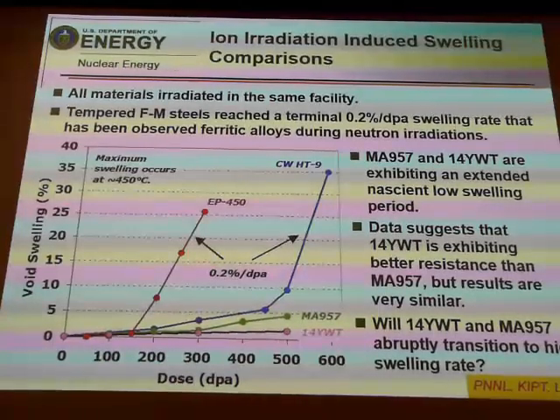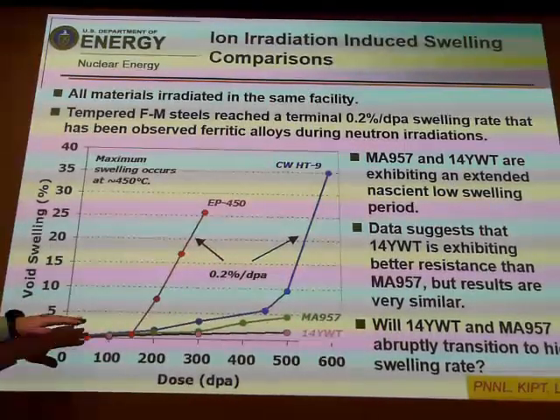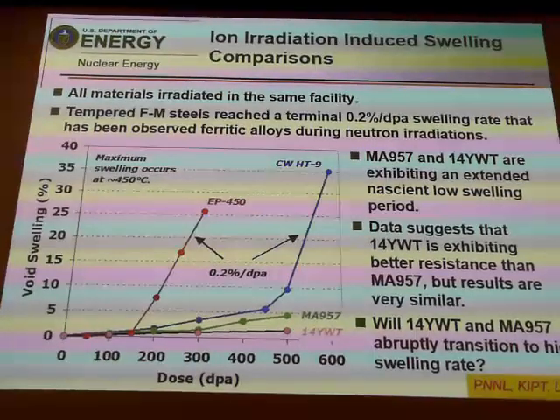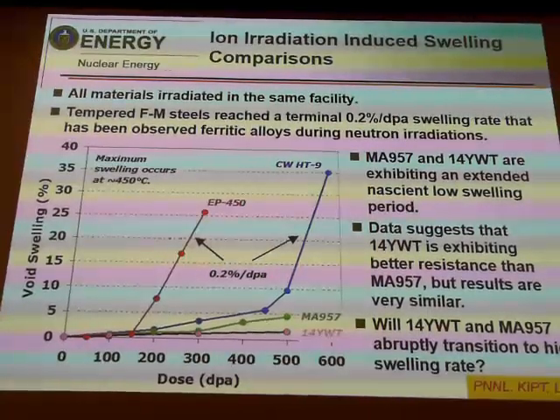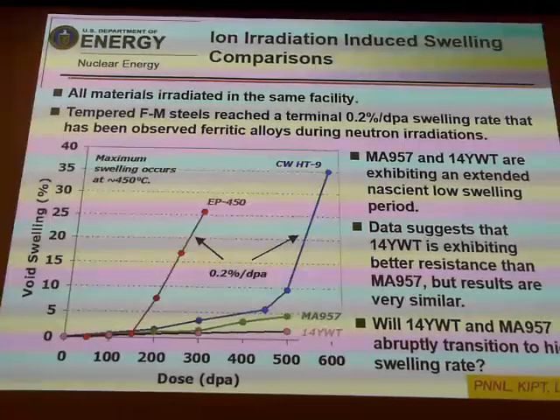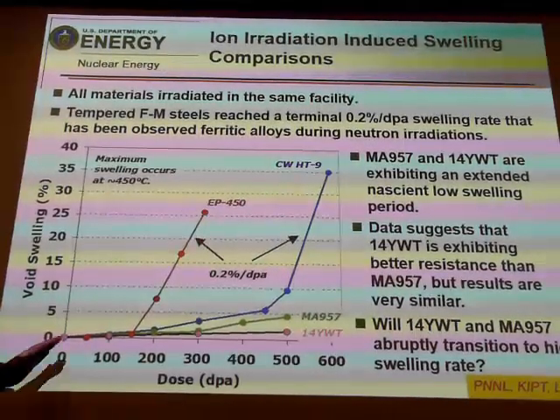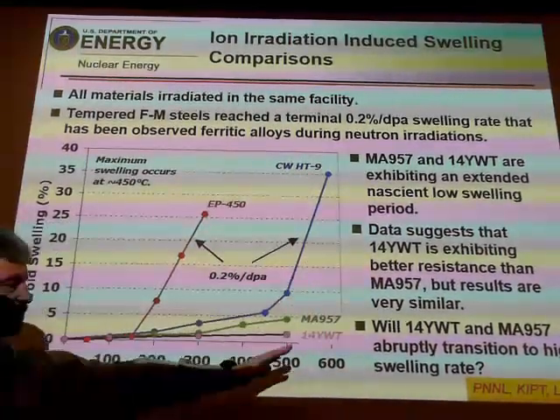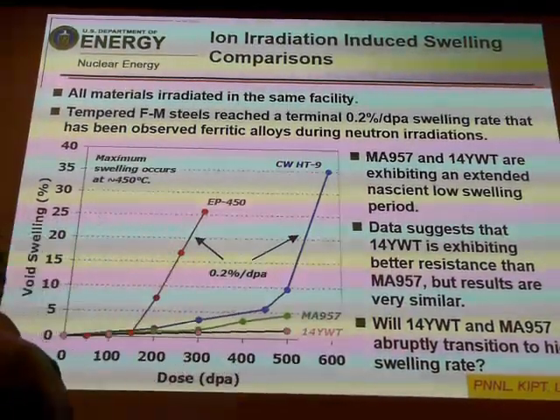Clearly, once you get over 5% void swelling, typically from an engineering standpoint, you don't really have something you can use much, but at least you'd only take off at 0.2 versus 1% per dpa. So if I put the austenitic stainless steels on here, they would be swelling here. And so ferritic steels push you way out to here. ODS, perhaps somewhere even further.